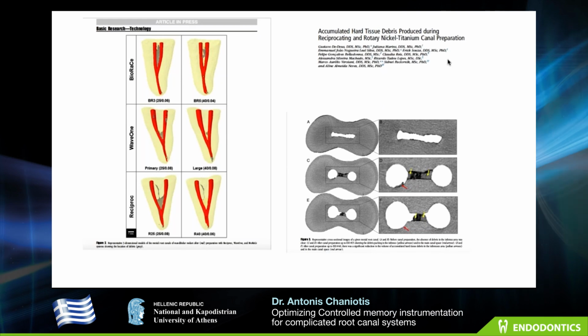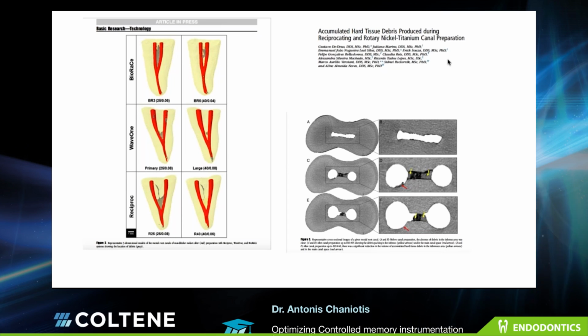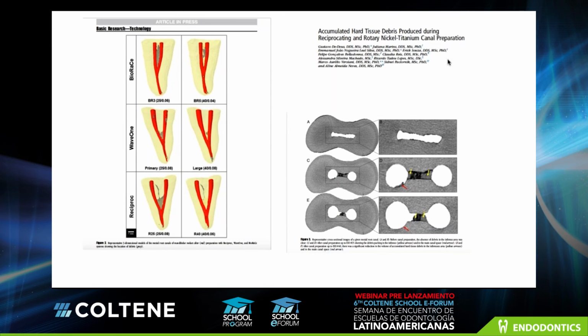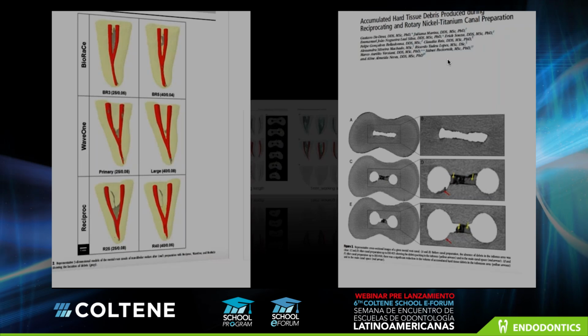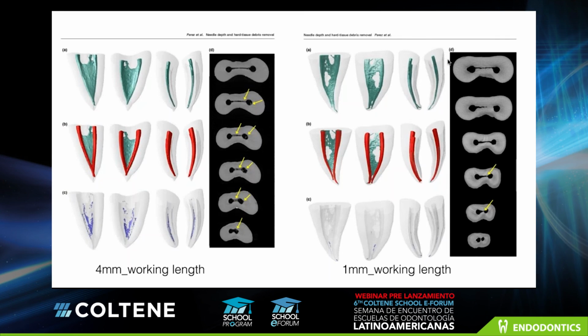In these canals, in this paper, increasing the size of the preparation from 25/08 to 40/04 or 06 with irrigation resulted in less hard tissue debris accumulation in the isthmus area and cleaner canals. And if you want your irrigation needle to reach the last apical millimeter, you need to enlarge the canals at least up to 30, because if you are using a 30 gauge irrigation needle, you need space to drive this needle to the last apical millimeter.